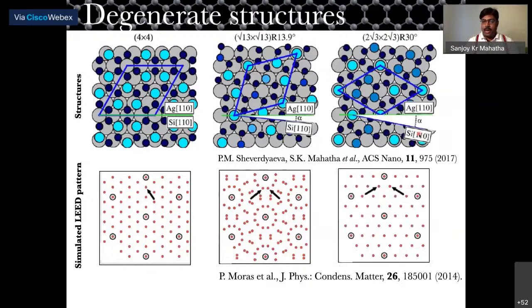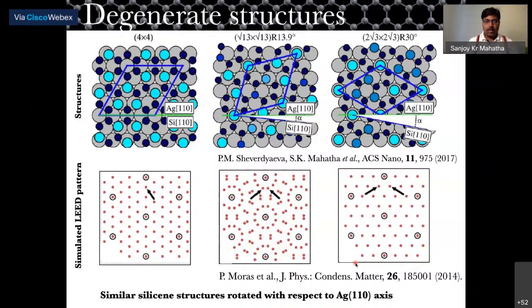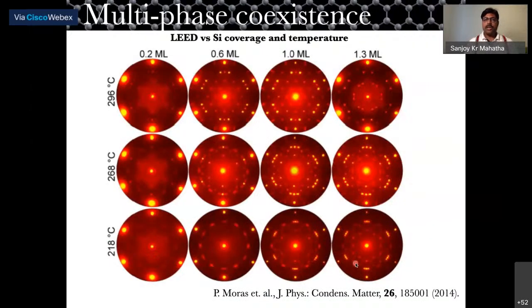In this case, these two spots are a bit far apart if you compare with root 13 by root 13. In root 13 by root 13, they are very close to each other. In 2 root 3 by 2 root 3, they are far apart. And what we did was grow silicon at different temperatures, and we tracked the intensity of these spots in the LEED pattern as a function of coverage.